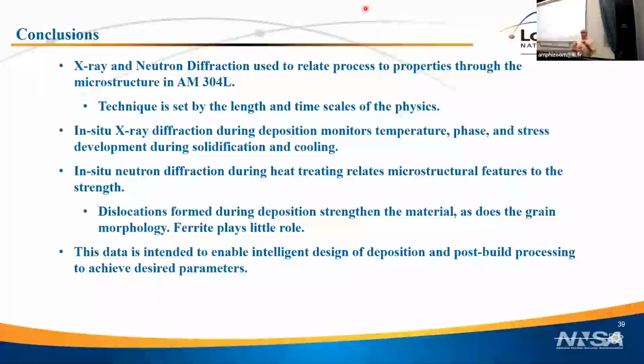The reason we published it is because there was an interesting thing. You can see the beta change to alpha, and you can actually see the d-spacing. Epitaxial is not the right word, but I guess the orientation relationship: the 110 of the beta and the 002 of the alpha form with the same lattice parameter within a factor of root 2, or root 3, there's a factor there, but they form the same. And then with a little bit of time, they separate. So there's some sort of constraint on the alpha as it forms from the beta, and you can see that change. That was why we did publish it. But you can't get anything absolute out of it because there's too many things going on.